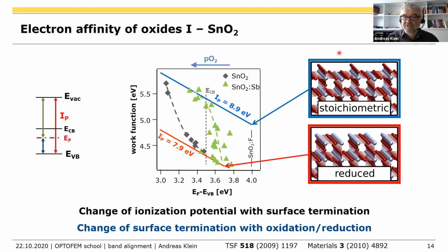So you can get a stoichiometric surface termination. All your tin atoms are 4+. So these gray ones are the tin atoms. Or you can have a reduced surface where you have tin atoms at the surface which are in the 2+ oxidation state. This gives a difference in the ionization potential, and of course then also in the work function, by about 1 electron volt.